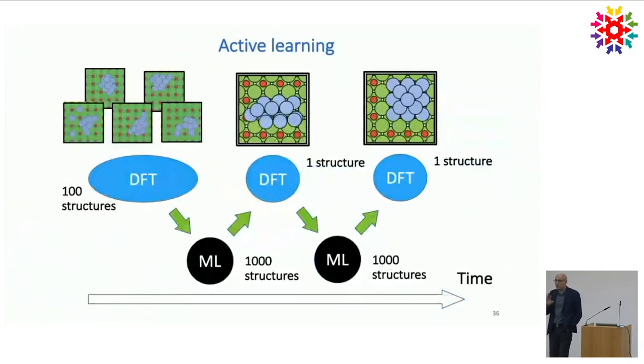So I promised to say something about how we trained the neural network, and it's given here. So basically, we had to start out from something. So we had about 100 DFT structures that the initial neural network was trained on. And then we let it loose and did the basin hopping search. So we perturbed one structure and relaxed it via steepest descent into the nearest local minimum. And then the data that was generated there was still at the model level, because otherwise we could not have done it. But then the final structure was done at the DFT level, added to the training data, a new round of optimizing those W's in the neural network was made, and it was now a more accurate neural network, and we repeated this process over and over again.